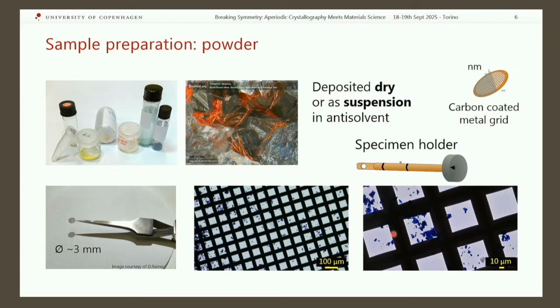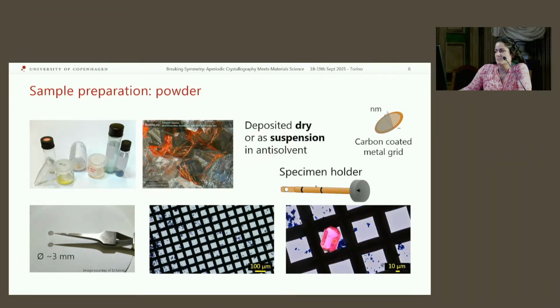The grid itself is just 3 millimeters. You can see the blue crystalline grains here dispersed on this film, and all the grains that we see here are actually too big for electron microscopy and diffraction, but we have many more that are much smaller. And just to compare, if you want to do X-ray diffraction, for example, you need to grow a crystal in proportion of this size, so several tens or better, hundreds of micrometers.